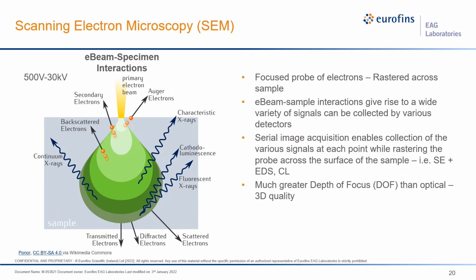In this case, we're going to use a focused probe of electrons, not light as in the case of the scanning laser. We can vary the energy of the electrons from about 500 volts up to 30 kV in most cases in our systems. The interaction of this primary electron beam with the sample generates all kinds of useful signals that we can have different detectors for. And so we can collect this data at the same time.